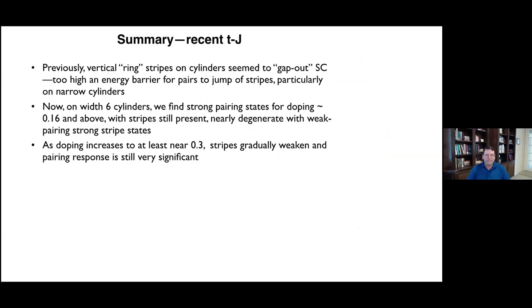To summarize these recent TJ results: previously, these vertical rings of stripes on cylinders seemed to gap out the superconductivity. A particular ring might like exactly four holes and not two or six, so it would be too high an energy barrier and we wouldn't see the superconductivity so well. But now, with better techniques and more states, we find some new stronger pairing states for near optimal doping. They still have stripes present, but with near degeneracy with the weaker pairing, stronger stripe states. And as the doping increases to quite large doping, the stripes gradually weaken and the pairing response is still significant, but falling.